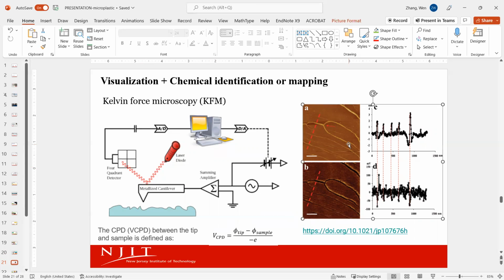So in our previous work, many years ago when I was a student, we used this technique to map quantum dots and nanoparticles, as well as even DNA polymers. DNA is a polymer. They generate different contact potential differences. This is related to the work function difference between your tip and the sample. Your sample is always different from your tip, which is usually a platinum AFM tip. So once you generate the work function difference, you can differentiate the materials based on the contact potential. This is another way to not merely visualize, but also tell you what they are, right?